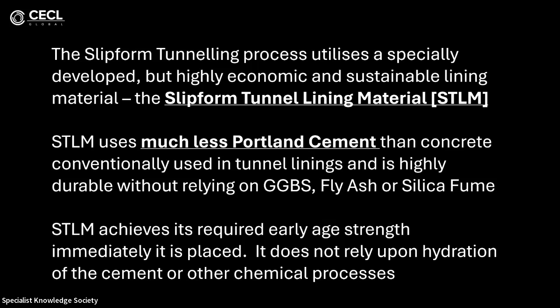So the mix itself has many of the components you'd see in a conventional concrete, so aggregates, cementitious binder, water, steel fibers, polypropylene microfibers, but it's formulated in such a way that it's enhanced by this mechanical process to give us this very early age strength and stiffness. So the binder component of it uses Portland cement, which is replaced with partial replacement with limestone and calcined clay, supplementary cementitious materials, and overall has quite a low Portland cement content.